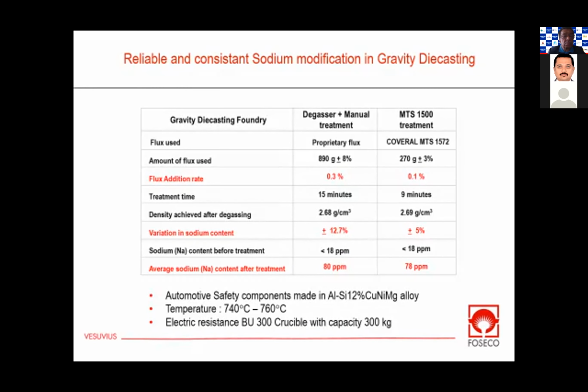Because when the cooling rate of the casting is not sufficient, when you try to use strontium modification, you sometimes have shrinkage, residual shrinkage that the foundries cannot get rid of. For those reasons, I know many foundries around Asia and around the world who are still using sodium, because sodium is a much stronger modifier than strontium.